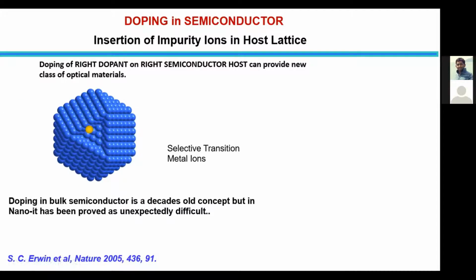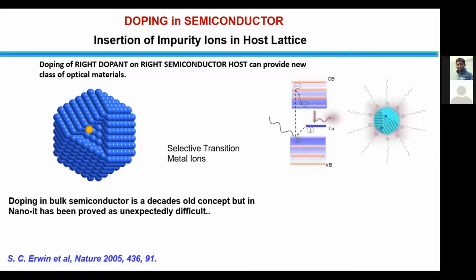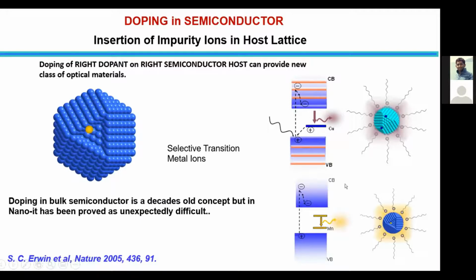and at the end, it creates a defect. Sometimes it creates a defect, sometimes it creates its own band level inside the valence band and conduction band. So you will have different emissions from the same nanocrystals by using the doping. And also if you see the manganese, it creates two levels. Exciton energy transfers from the host to manganese, and it can have an orange emission from there.